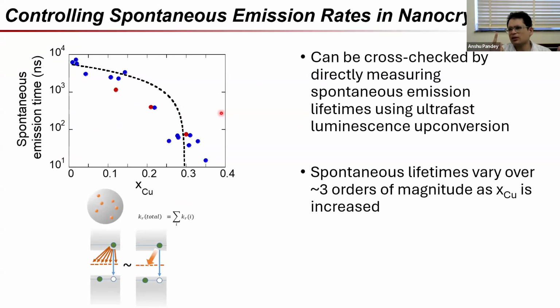In these measurements, because everything is timed with a laser pulse, and we wait for complete de-excitation before the next pulse comes, that also does not become a significant worry. So they are not worries as far as these experiments are concerned, but there is a separate point which you raised, which is very important: would you like to use these materials as biomarkers or in a biological application? Absolutely, yes. These will be better because these are much shorter time emitters than regular quantum dots. So there is a use which they'll have because they are doing it without a Purcell effect.